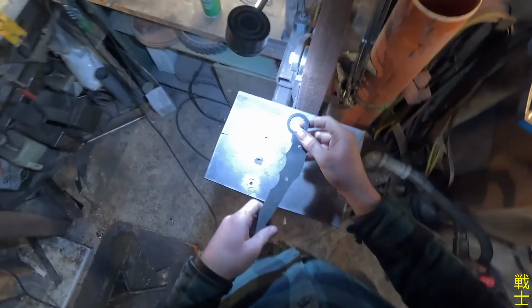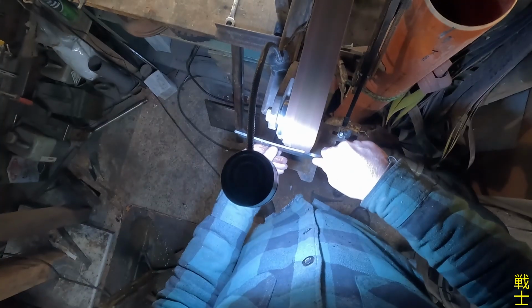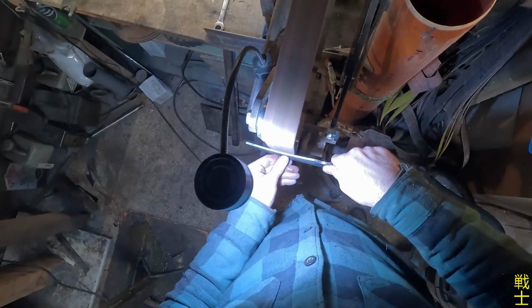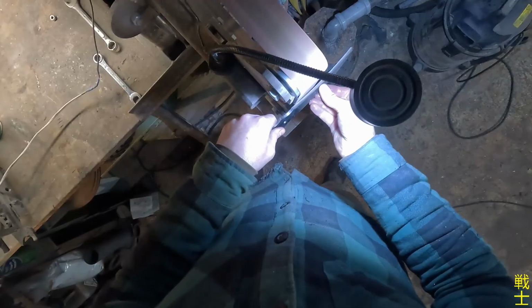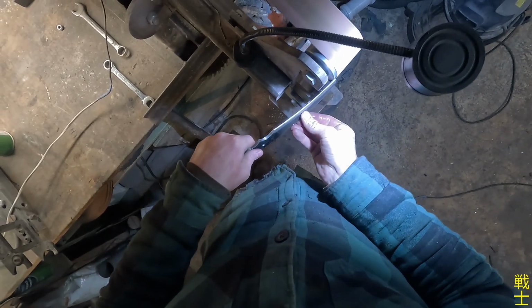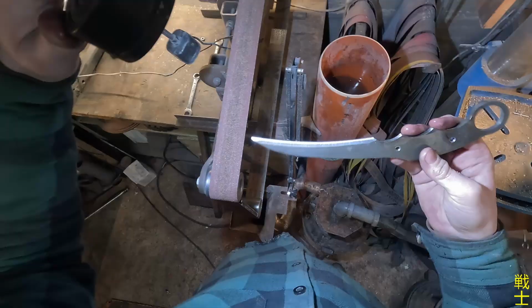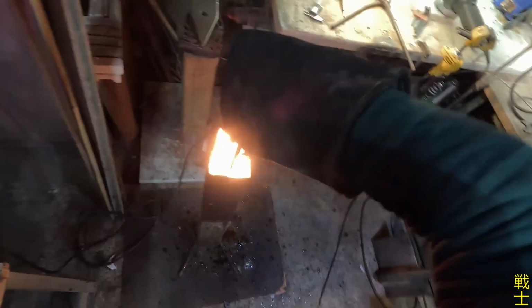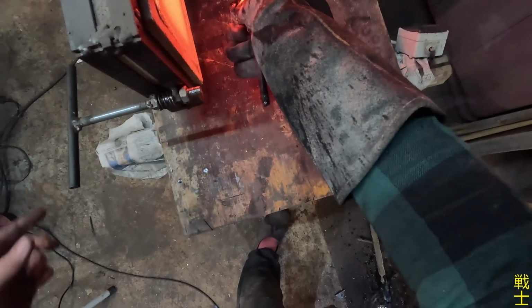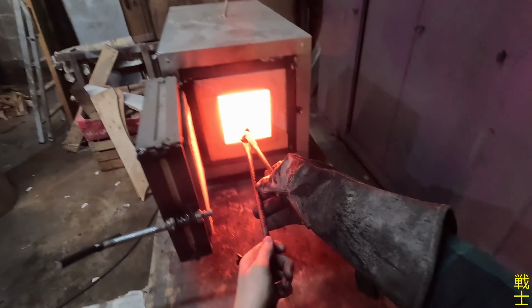This knife would be ready for heat treat right now, but with a steel this thick, I like to take off a bit of material on the cutting edge to ensure a quicker cool down during the quenching that ensures a hard edge. On the topic of quenching, I start that by preheating the oil with a piece of flat bar. This is needed to lower the oil's viscosity, which speeds up the cool down during quenching. To heat the steel to the required temperature of 1050 degrees Celsius, I use my self-built electric kiln. After reaching the temperature, I hold it for 15 minutes before quenching the knife in the preheated oil.